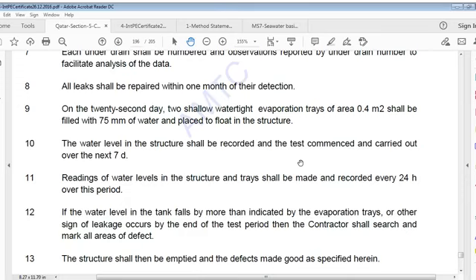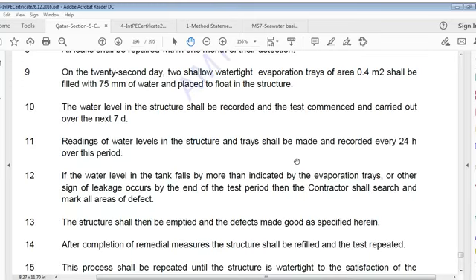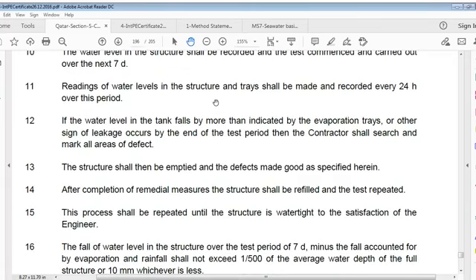On the 22nd day, two shallow watertight evaporation trays of area 0.4 square meter shall be filled with 75 mm of water and placed to float in the structure. Water level in the structure shall be recorded and the test commenced and carried out over the next 7 days. Readings of water level in structure and trays shall be made and recorded every 24 hours over this period. If water level in the tank falls by more than indicated by evaporation trays or other sign of leakage occurs by end of test period, the contractor shall search and mark all areas of defect.